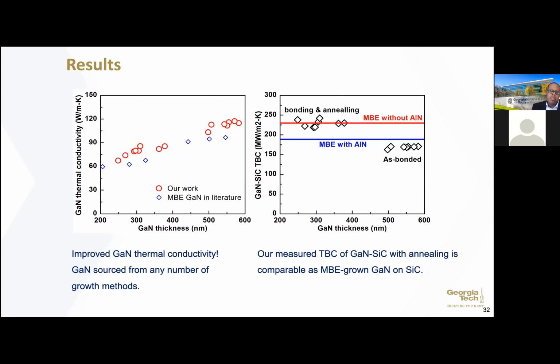So when I grow this material on sapphire, I can actually grow high quality gallium nitride that I can then bond directly to this silicon carbide layer. If you do MBE growth directly on silicon carbide, what you see is that you actually get a lower thermal conductivity because it's not the electronic grade version. So we're able to get fairly good thermal conductivity of this particular layer. But what you also see is this comparison at the as bonded.